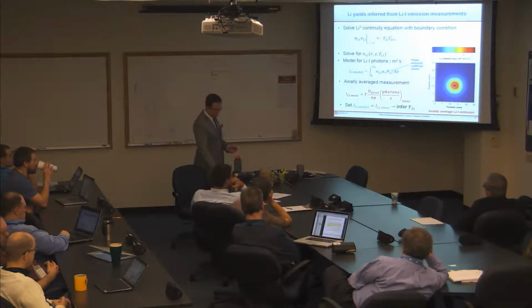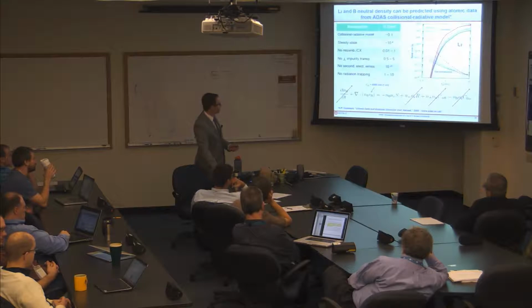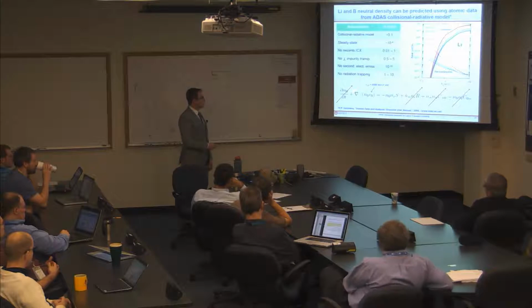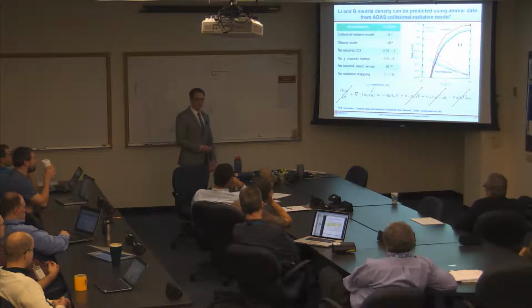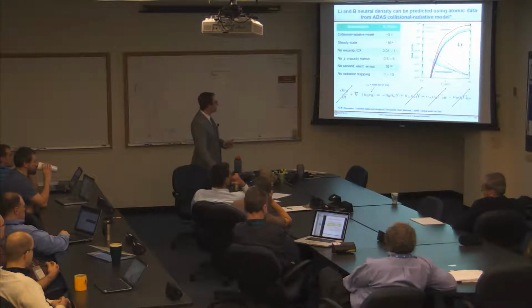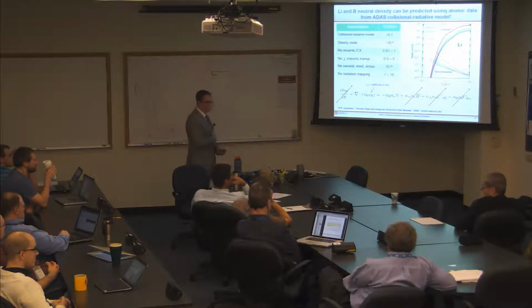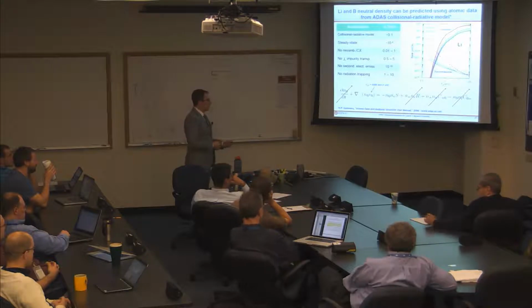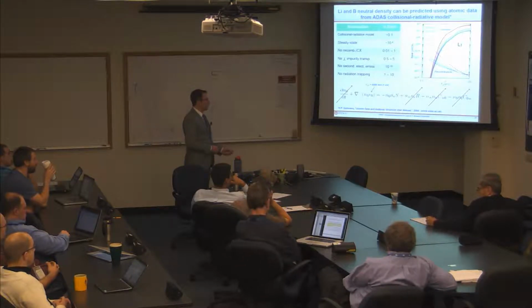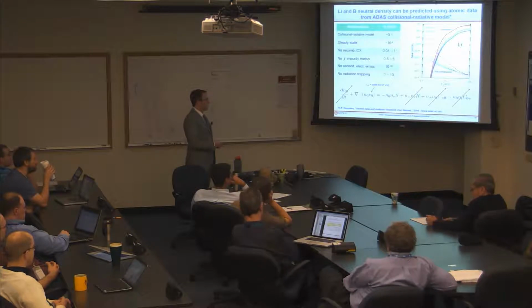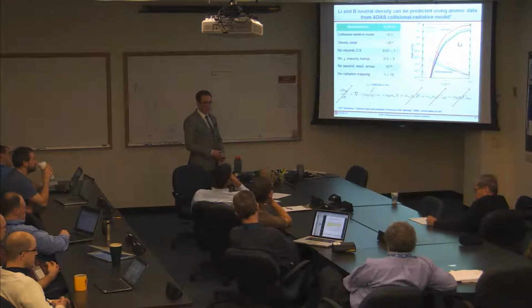What density is that term? Well, I think it should just be linear, more or less. So if you went up another factor of 10, so if you're at like 10 to the 15 per centimeter cubed, since I've been using centimeter cubed. Now, radiation trapping isn't in the equation at the bottom, is it? No, that's not something you need to put into the continuity equation. That would be something you need to worry about in inferring the lithium erosion rate from the density. So the idea is that radiation doesn't get to you because it gets trapped on its way out. Right, that would be the worry, yeah.